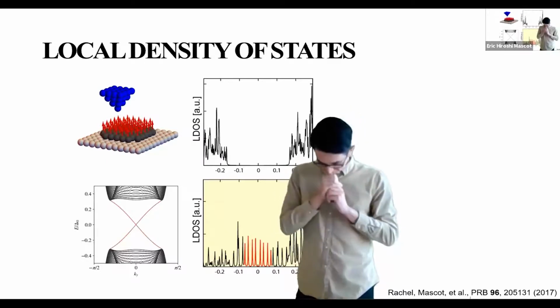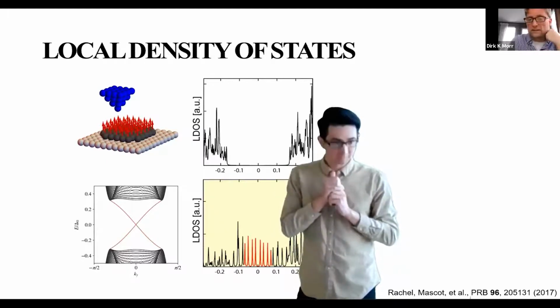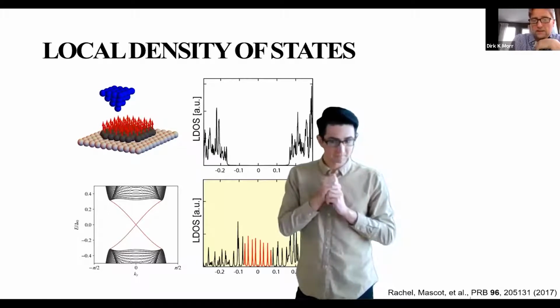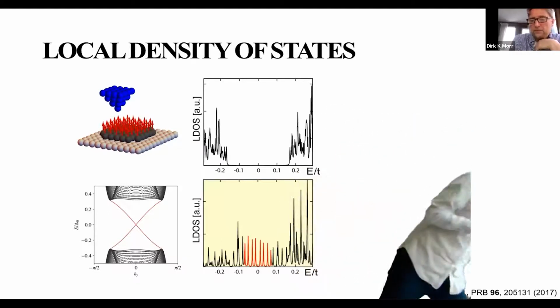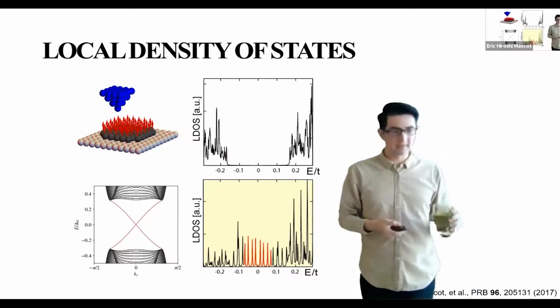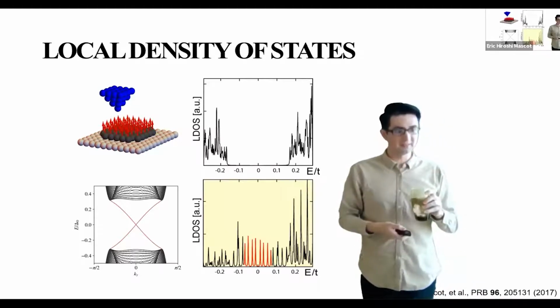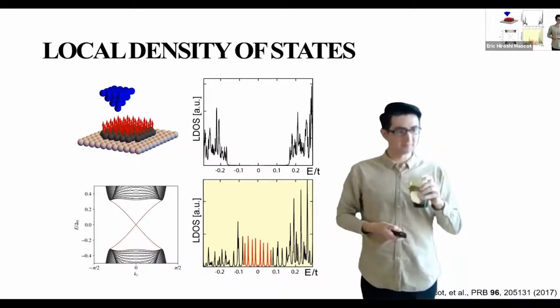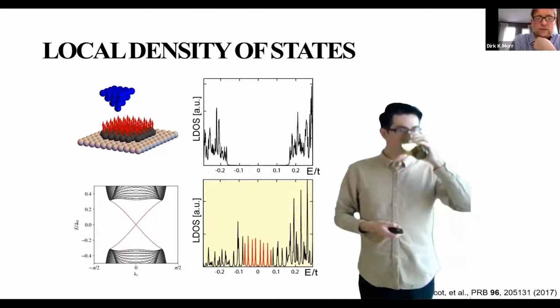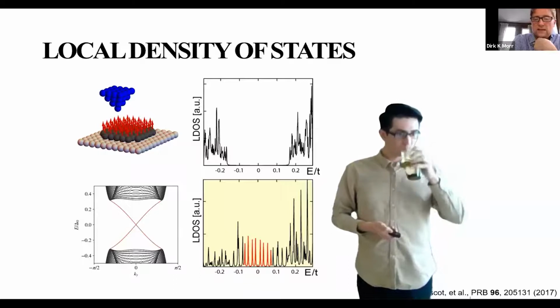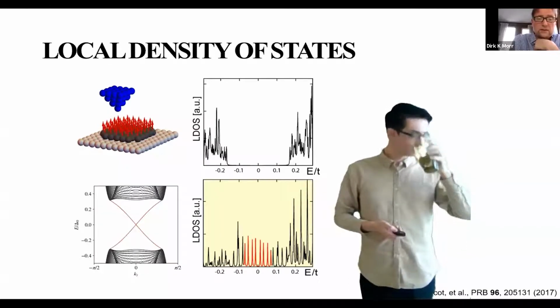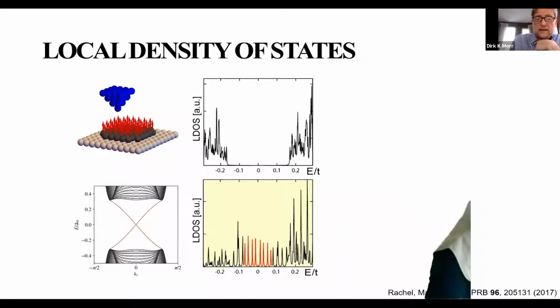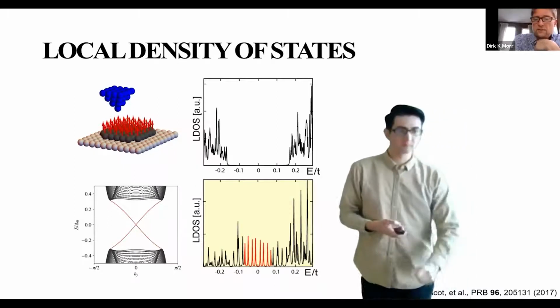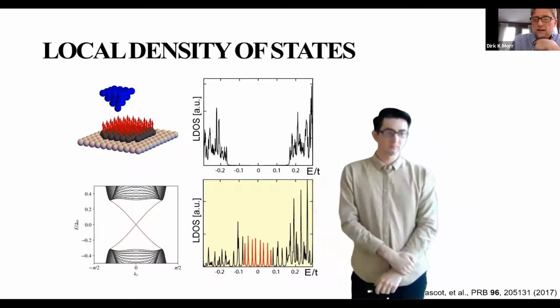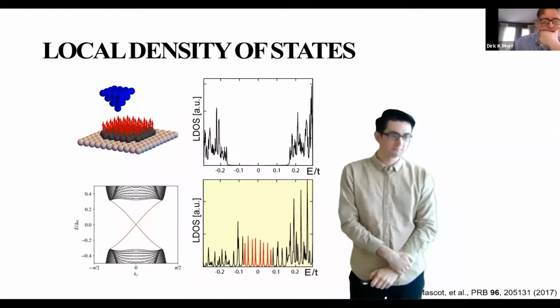Okay. And experimentally, when they build these systems, they see that the gap is reduced, but it's still there. Yeah, it definitely is suppressed from the magnetism. But as Eric said, one of the interesting results that we found is that the Rashba spin orbit interaction seems to stabilize the gap for much larger values of the exchange coupling than you would expect. Eric? Yep.